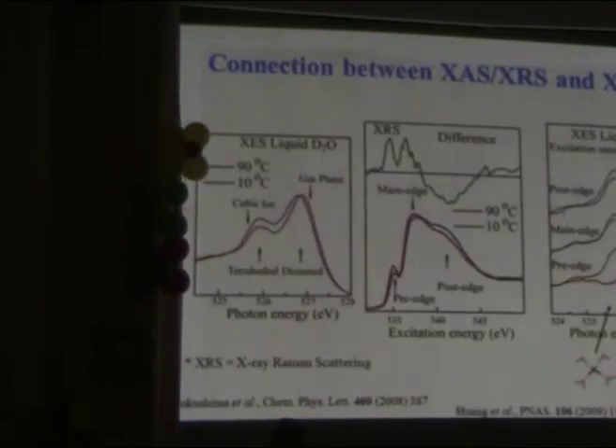We can connect the two spectroscopies because X-ray emission comes after the absorption, which means that we can use the photon energy to select where on the liquid spectrum we do the excitation. We need a reference, and the reference will be at 550 eV, where there's no structural sensitivity. The reference is this black line here.